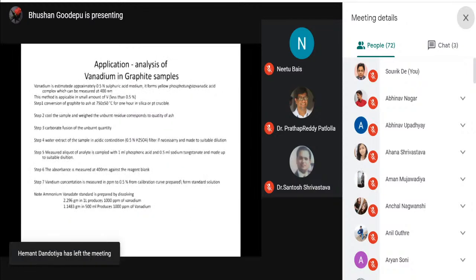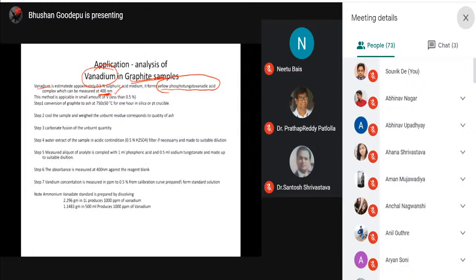Now we have carried out a very challenging task of analyzing vanadium in graphite samples. Vanadium forms a complex, which is measured at 400 nanometers. The vanadium is estimated as a yellow phosphotungstovanadic acid complex. At 400 nanometers, it is measured by utilizing sodium tungstate, used along with phosphoric acid in a sulfuric acid medium.